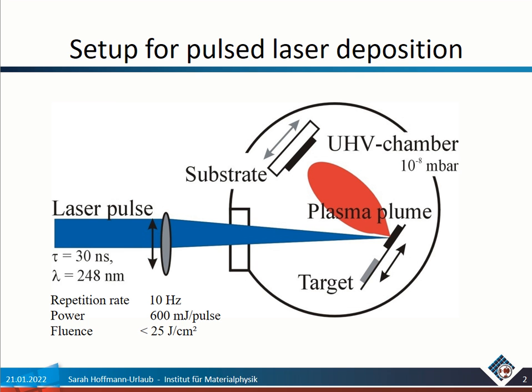If you're not familiar with pulsed laser deposition in detail, I will shortly explain this technique to you. So we have here a typical setup where we couple our laser pulse of wavelength 248 nanometers, so in the UV range, and a pulse length of 30 nanoseconds. We couple it via a lens here that's rotatable into a UHV chamber. The base pressure can be up to 10 to the minus 9, but this is only for chamber number 3. The other chambers are 10 to the minus 6 to 10 to the minus 8 millibar before deposition.